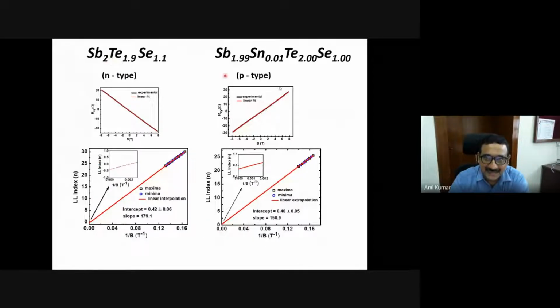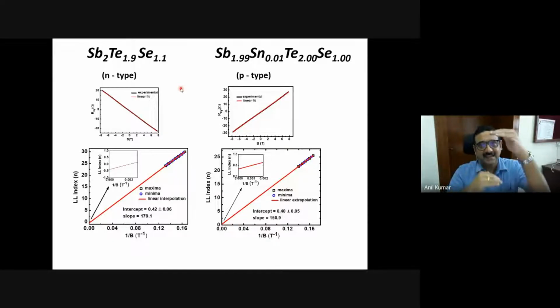So now the interesting part which I wanted to tell you is that, see, if you take this antimony tellurium selenide crystal, this is an N-type conductor. The moment I dope with 0.01 tin, it becomes a P-type material. And both give me pi Berry phase, topological material. In the earlier example, I told you that by applying gate voltages, I am tuning the Fermi level to make it either N-type or P-type.